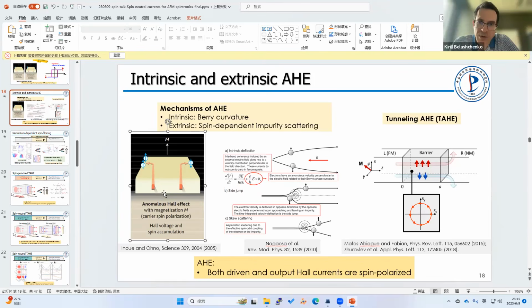Yeah, for sure. I mean, the symmetry conditions are the same for those. It's just that quantitatively, you can't say that the spin response is simply proportional to the charge response times some polarization. So the calculations show that this is not the case. They're given by different integrals, and they are integrated over the Brillouin zone, so they're weighted differently. So they're not just proportional through one factor. And you could have one of them accidentally vanish, for example, but the other be still finite.